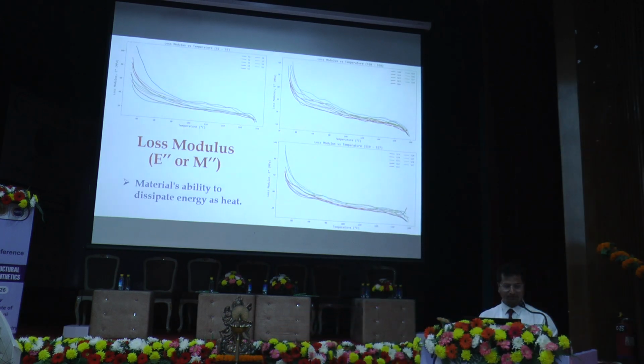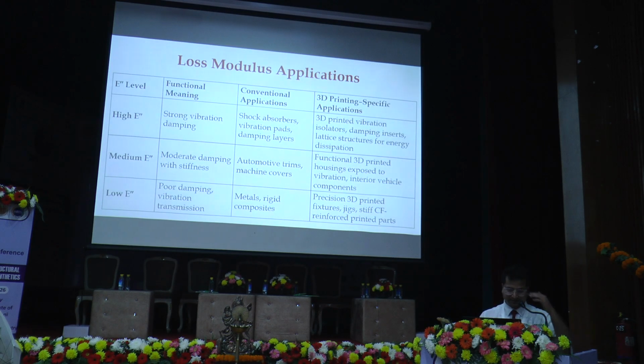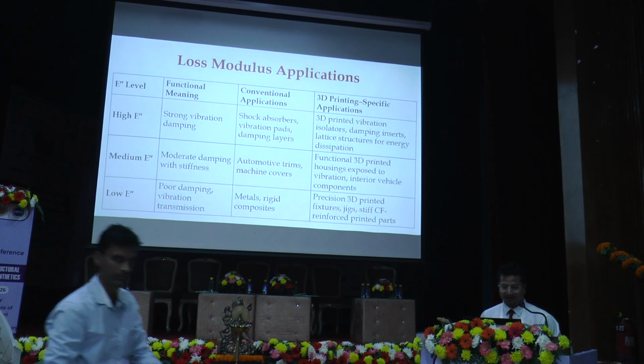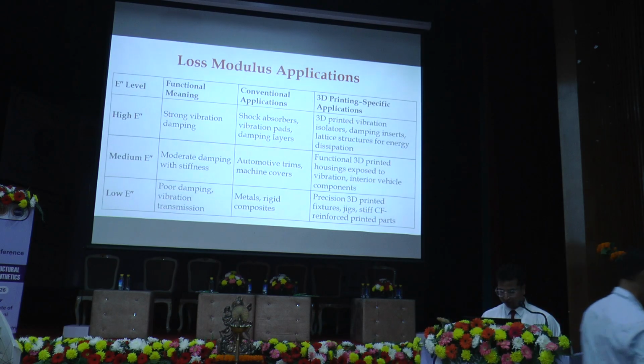Loss modulus is the material's ability to dissipate energy as heat. Similar case for loss modulus also. In my case, I would want lower loss modulus. These are the loss modulus applications. Its functional meaning is vibration damping, and in 3D printing applications, it's used in isolators, damping inserts, as housings, and several fixtures and jigs.